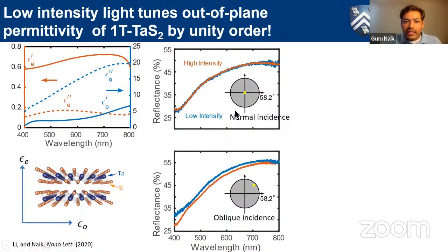If we take two different white light intensities, low intensity here about 10 milliwatt per centimeter squared, high intensity about 1000 milliwatt per centimeter squared, and this is the normal incidence case, I don't see any change in reflectance. But I go to oblique incidence, I see that the reflectance changes. So that was very surprising. And since it changes only in oblique incidence, and not in normal incidence, our idea was that only this epsilon out of plane, or epsilon C axis, is sensitive to intensity, not epsilon in plane, which is the ordinary permittivity.